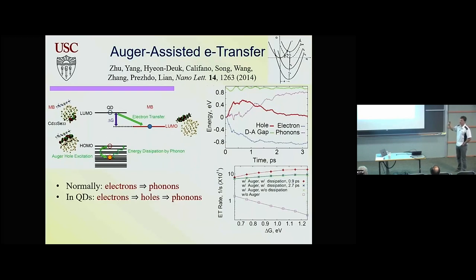Usually Auger energy exchange goes from electron to hole, because when you photoexcite, your energy mostly goes to the electron, the one that has lower density of states. That's where you put more energy in. So I think this is more relevant when you have energy in the electron. And do you expect a Marcus inverted region in that case or not, for hole injection? The Auger processes will still be important. Maybe not actually, because you can still have that. I think it was shown for both. Tim showed it first, I think, for the electron, right? And then Paul had a postdoc working with him showing the same physics for the hole too. It's just that the Auger scale is very fast.